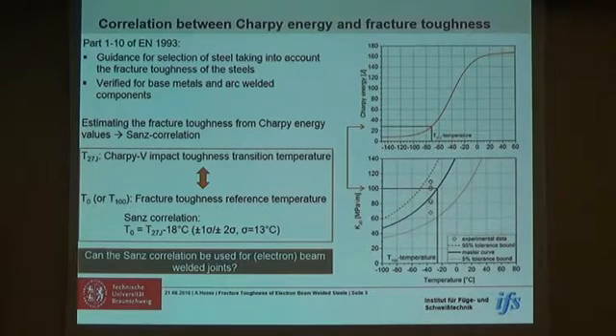We are not the first ones to think of this scenario, but it has been used as a scenario for standards, especially in Eurocode 3, part 1-10, which is a guidance for the selection of steels taking into account fracture toughness. It has been verified for base metals and arc-welded components. And one central element that they use is a correlation between the fracture toughness taken from Charpy energy values and the T0 temperature from the fracture toughness master curve, known as the fracture toughness reference temperature.